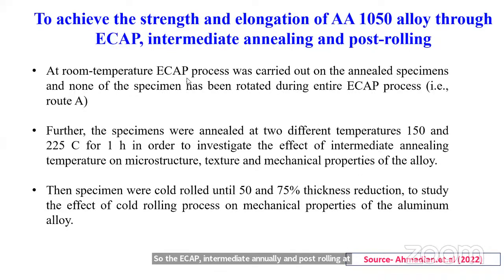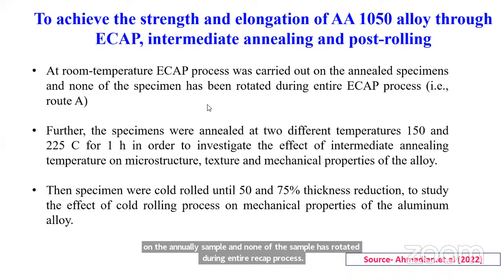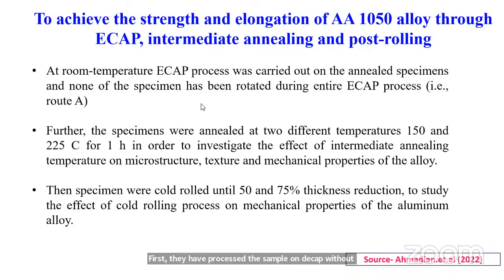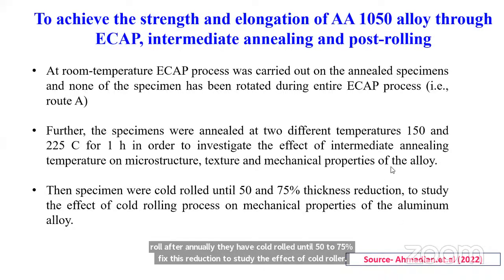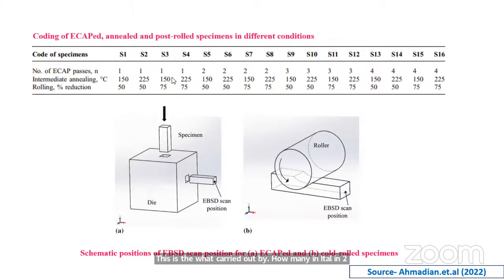First, they have processed the sample on ECAP without rotating, without rotating the samples either to plus 90 or minus 90. Whatever the direction the component is coming, the same direction they have passed. Then the samples were annealed at two different temperatures, 150 and 225 degrees centigrade for 1 hour, to investigate the effect of the intermediate annealing temperature on the microstructure. And the specimens were cold rolled. After annealing, they have cold rolled until 50 to 75% thickness reduction to study the effect of cold rolling. This is the work carried out by Ahmadian et al. in 2022. You can see these are the results they have obtained.